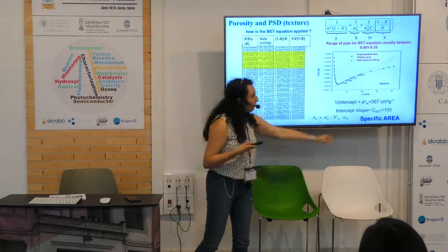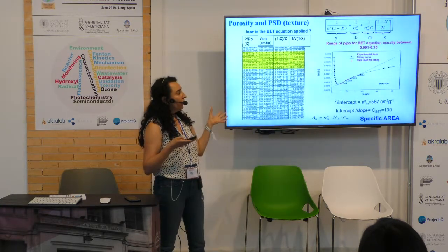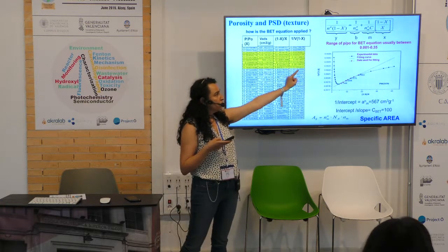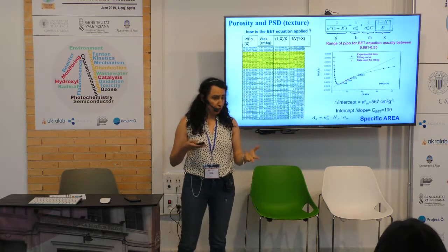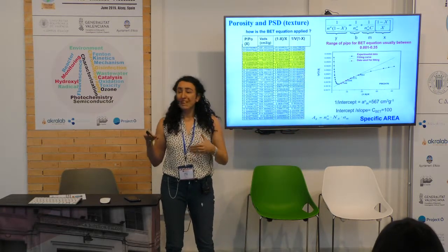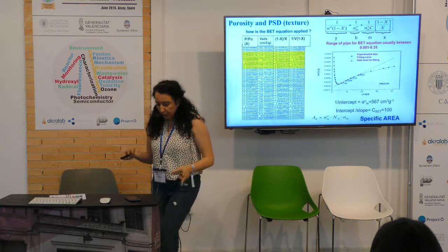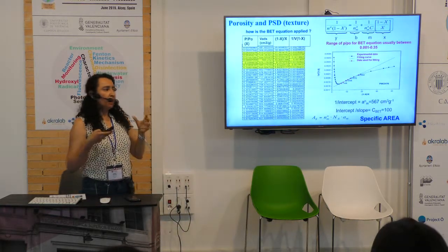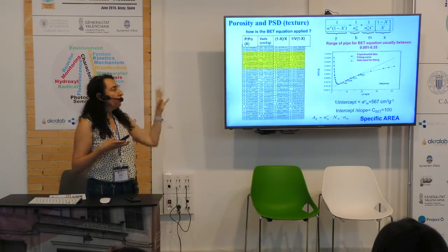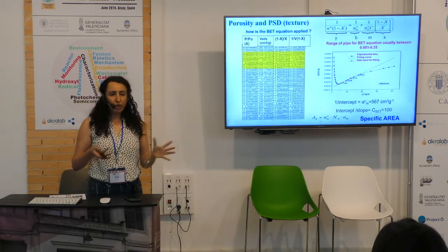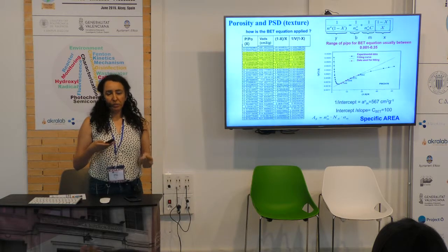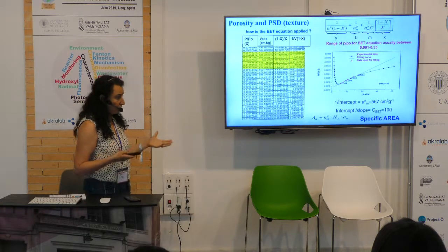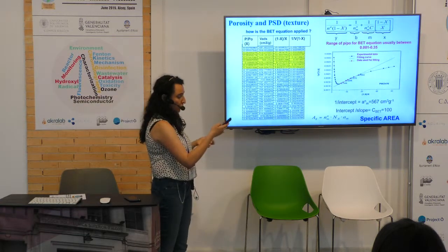So if you keep going, there will be a place, which is usually between 0.001 and 0.35 of relative pressure, where the BET equation should be linear. And I mean should be, because it's not always the case, meaning that if your material cannot be fitted into this equation, don't even bother. The real experiment is the isotherm. Sometimes you simply cannot estimate the surface area by these different equations.